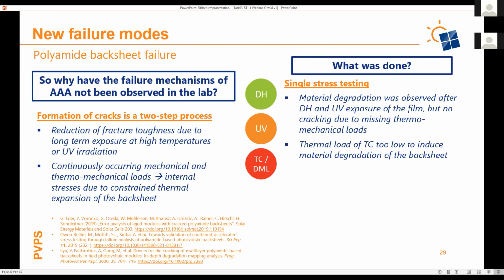So what was done? Back then, single stress testing was state of the art. So they made materials, the films, they made mini modules, put them into the climate chamber, in a UV chamber, in thermal cycling. But it was never the same module going into this test - it was one module for damp heat, one module for UV, one module for thermal cycling.